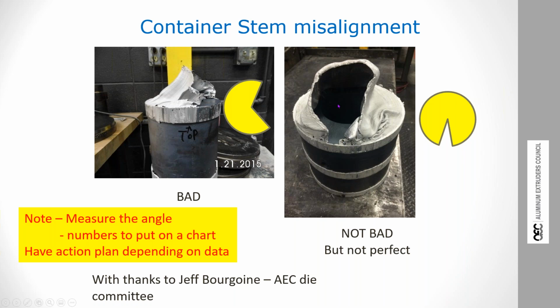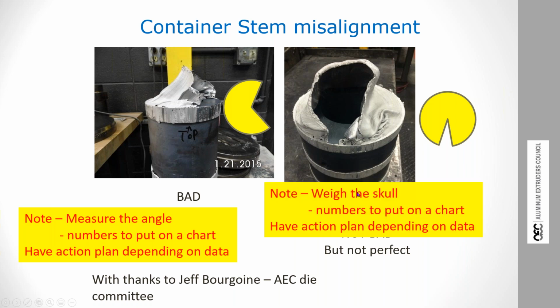The second thing I would do with this is I would take a knife or a chisel and I would remove the skin, or weigh the block before and weigh the block afterwards, and I would weigh the skull. That tells me the average thickness of this layer. That tells me how my dummy block is expanding. If I plot this over time and keep a record for each dummy block as it comes back to the press, I can watch that creep that Danny talked about. I can predict when the dummy block is going to come to an end.